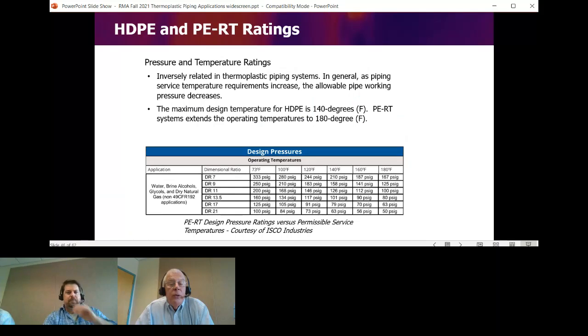Pressure, as all thermoplastics go, as temperature increases, the working pressure decreases. As you can see, for a DR7 it goes from about 300 psi at 68 down to 167 at 180. So basically, as you increase the temperature, it requires you to decrease the DR, or use a thicker wall section, to accommodate for that expansion, or that loss in strength.